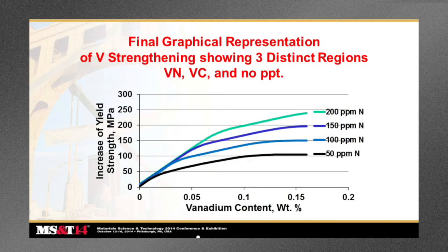And then finally, we know that nature doesn't work in straight lines. It definitely works in curves. In fact, if you tried to generate this model based on actual production data, it would be very difficult to actually determine where these inflection points are from vanadium nitride to vanadium carbide to vanadium nothing, because there's nothing available. What you will see is more or less a continuous curve that's gradually approaching a zero strengthening rate.